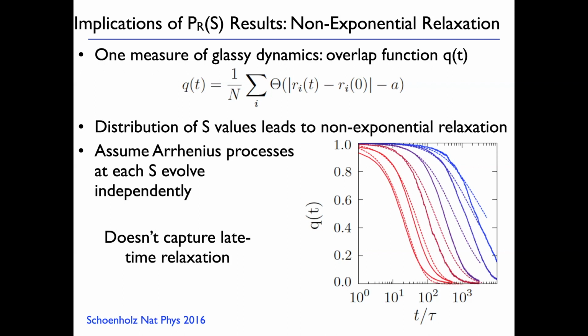So suppose now I just say each particle has a softness, and I just have these Arrhenius processes, because the probability of rearranging is Arrhenius, and at each softness they just evolve independently. Each particle just evolves independently with its Arrhenius relation given by its softness. That gives me the dashed lines. It's not too good compared to what we actually measure, which are the solid curves here. So it doesn't really capture the late time relaxation.